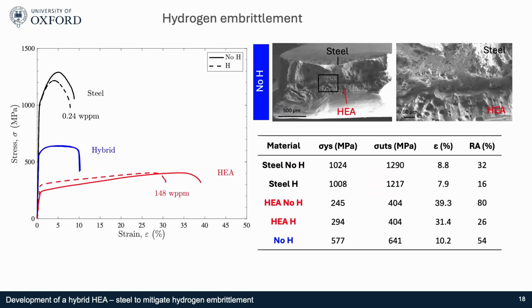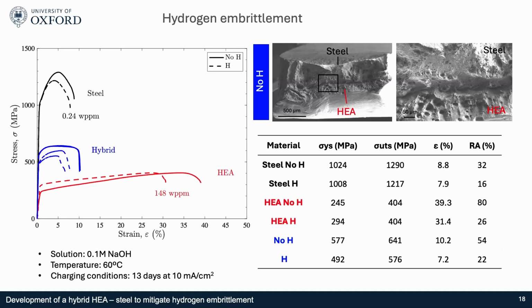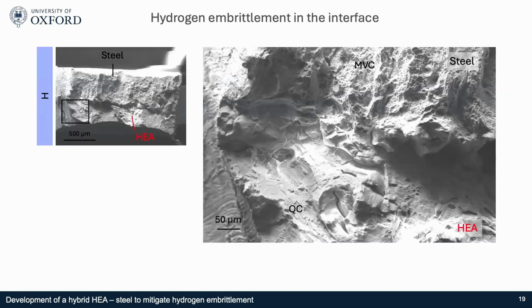So for the hybrid material, you can see here in the micrographs, before introducing hydrogen, we have the two materials, the steel and the high entropy alloy, and there are microvoids in both, separated by this valley along the interface. And after introducing hydrogen also for 13 days, we can see a reduction of properties also. Okay, so what happens in the fracture surface after introducing hydrogen?